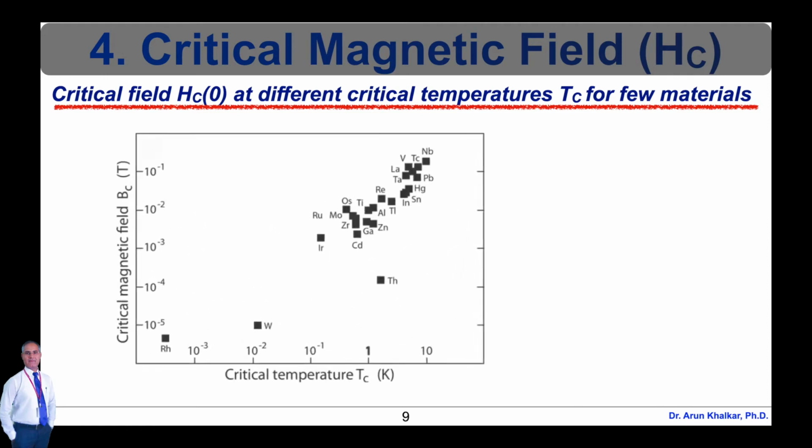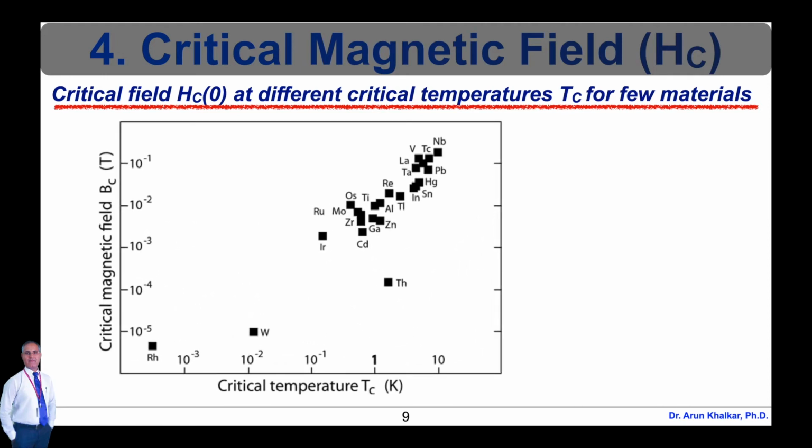The critical magnetic field required to destroy the superconducting state is strongly correlated with the critical temperature for superconductors. Each of these parameters can be viewed as representative of energy which can be supplied to the material in such a way that it interferes with the superconducting mechanism. This is consistent with the idea that there is a band gap between the superconducting and normal state.